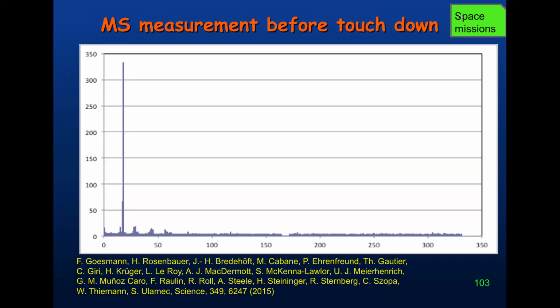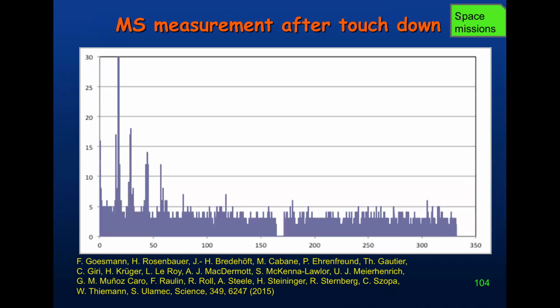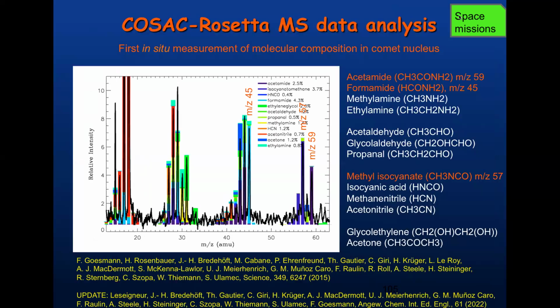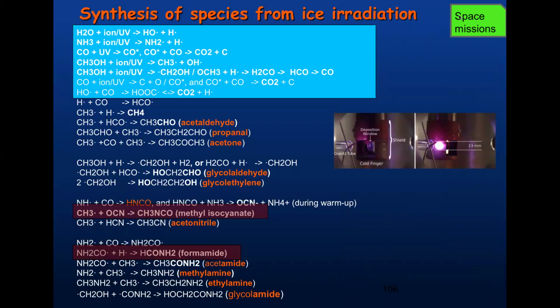This was before the dust was ejected, and this is after. So you see an increase of the masses, right? And I worked on the characterization of the molecules that were in this cometary dust. And you see that they are COMs. They are relatively large molecules. So we were happy with this result. And furthermore, you can see that most of these molecules in the comet can be made by 2 radical reactions, like it happens in the ice experiments.